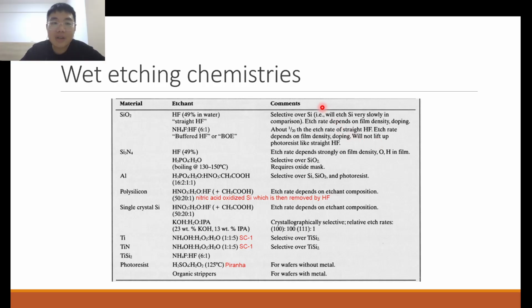So let's take a look at some wet etching chemistries. For SiO2, it's an oxide, so it makes sense to use an acid, and it turns out HF is very good. However, HF is a big health hazard, because if HF contacts your body, it's not just corrosive as an acid, but the fluoride ions will react with the calcium ions in your body and cause a kind of decalcification of your body chemistry. So you have to use an antidote if you ever come into contact with HF directly on your skin or on your eyes, things like that.